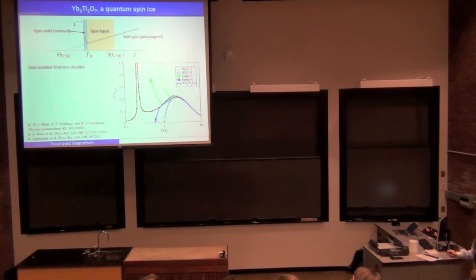And if you look at the heat capacity of the ytterbium titanate material, which is shown in the black curve here, you see a very broad bump at around 2 to 3 K. And below about 300 millikelvin, you see a very sharp peak. And this peak indicates the possibility of a long-range order, but this very wide bump actually tells us that the spin-spin correlation starts to develop around this temperature. So actually, at temperatures higher than this peak and around this bump, we have a correlated spin situation, so where we might find spin liquid.